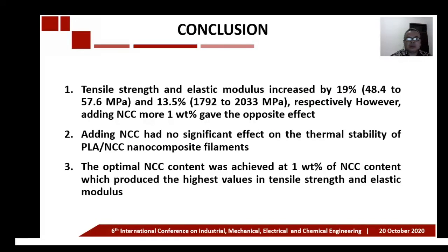And the last one is the conclusion. From the study, I can draw some conclusions. First, tensile strength increased by 19%, and the elastic modulus increased by 13.5%. But if we add more than 1% of NCC, the tensile strength and elastic modulus decrease.